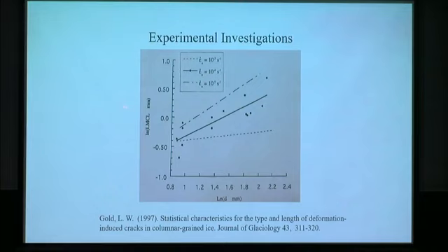So this is log mean averages of these crack lengths versus, I guess D is the grain size. We can see that for different strain rates, 10 to minus 3, 10 to minus 4, 10 to minus 5. So this is relatively fast rate of loading. Basically we can see that the nucleated crack size essentially scales linearly with D in the log scale. I think this is in the log scale.